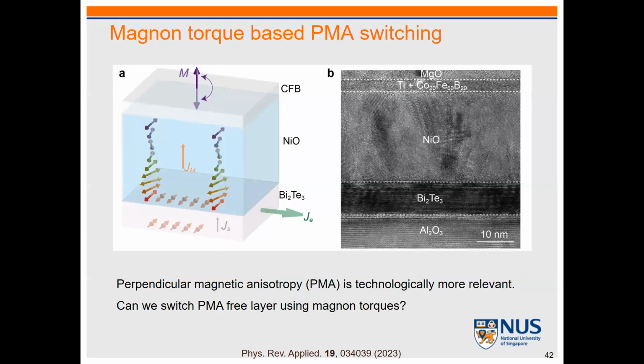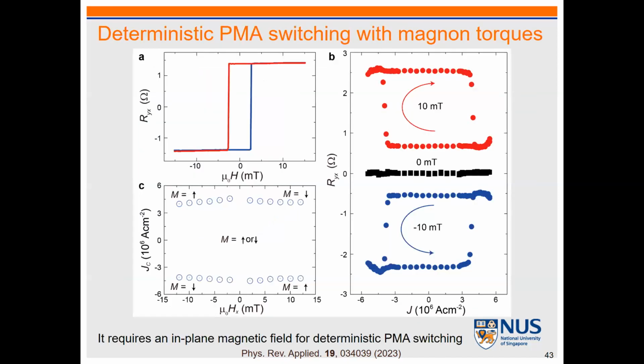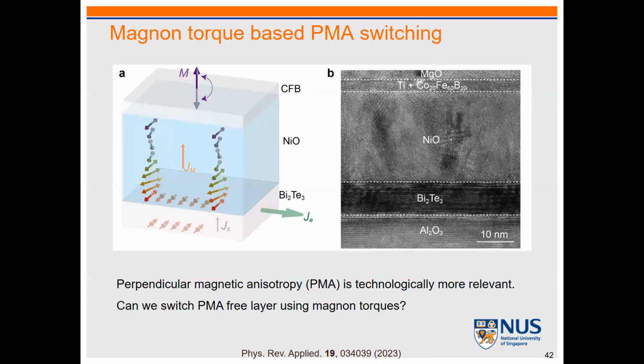So as I mentioned, our next mission is whether we can switch PMA. So we can fabricate this CoFeB film on top of this very thick nickel oxide, and we try to switch this using magnon current. And without any external magnetic field, we cannot switch, because our injected spin from bismuth telluride or bismuth selenide is only in-plane. So it exactly follows our conventional knowledge of typical spin Hall or Rashba systems.